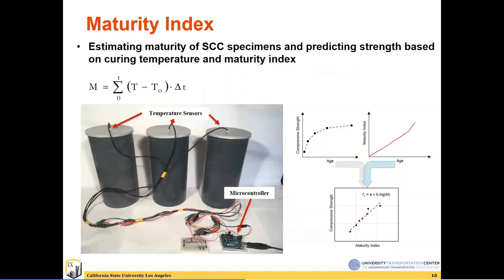Another big thing specifically in the application of the SCC for precast tunnel segments is the curing process for the tunnel segments and how the temperature gradient or the temperature difference between the curing process and the storage process could affect the performance of the precast tunnel segments. So to do that, we are trying to monitor the maturity of the concrete samples or SCC samples by monitoring the internal temperature over time and see if we can correlate the maturity index to the compressive strengths.